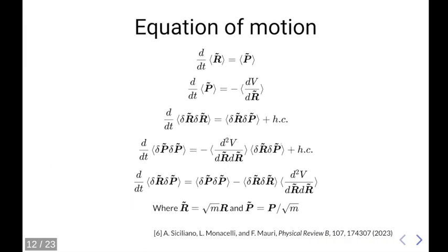And by deriving these equations, we actually can get equations of motion for all the parameters of the Gaussian wave packet, which are the average position of each nucleus, their average momentum, and then since we are describing quantum fluctuation, we have also correlators. For example, position quantum correlator, momentum, position-momentum, which define our Gaussian wave function or density matrix, and essentially it's describing the quantum nature.